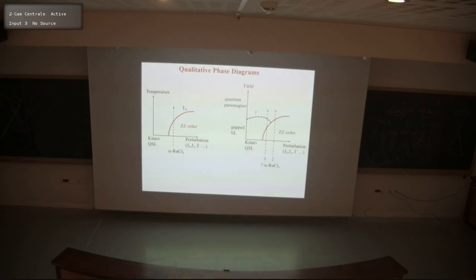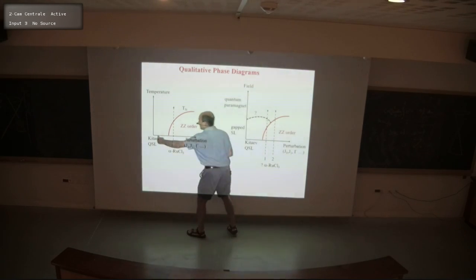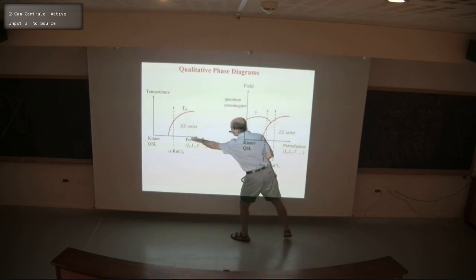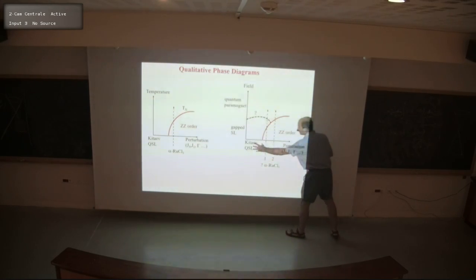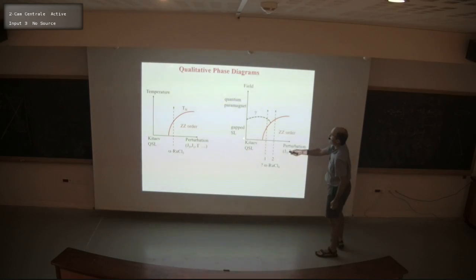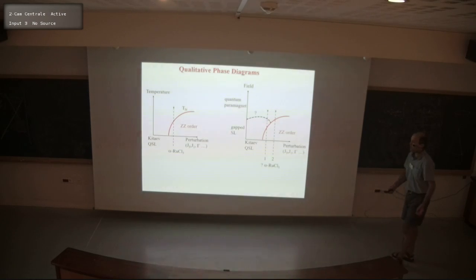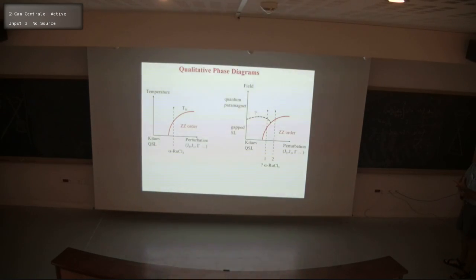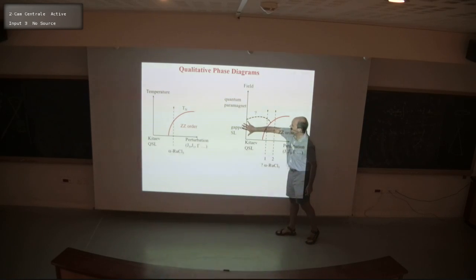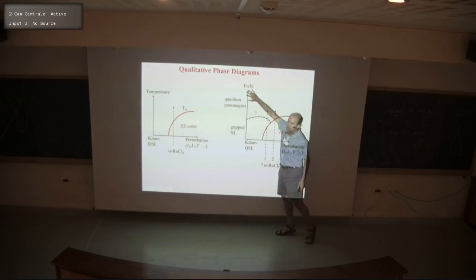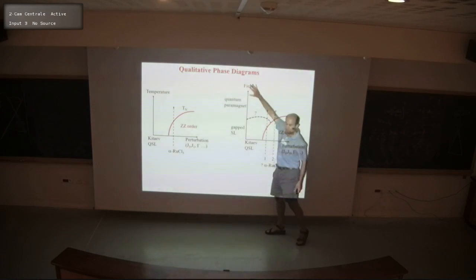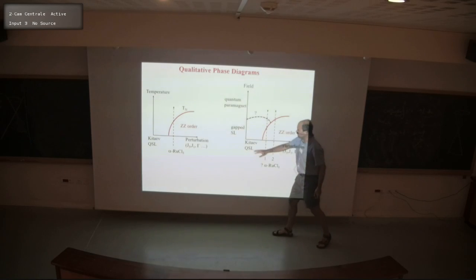Now, turning to measurements in applied magnetic field. Imagine you put the magnetic field along this axis, so I'm just going to show this plane. This is the perturbation that takes us away from the Kitaev spin liquid, stable up to this point. Now we apply a magnetic field along a direction that, as Lucille explained, has to have components along all three directions to get a gapped spin liquid. That happens immediately, as one opens a gap at some h cubed order in the pure Kitaev spin liquid. So this phase must have another phase transition going up to infinite field where the spins are polarized, because this is a product state. This is known, about 5% of the main coupling.